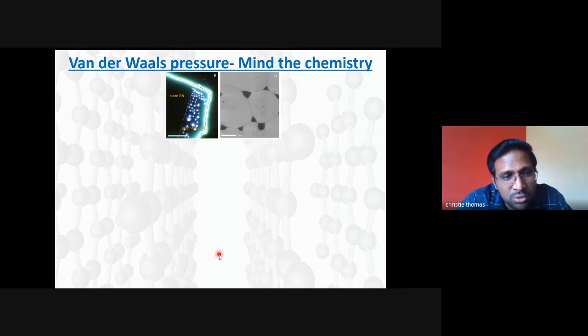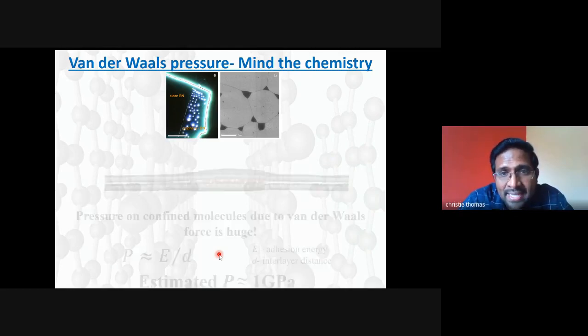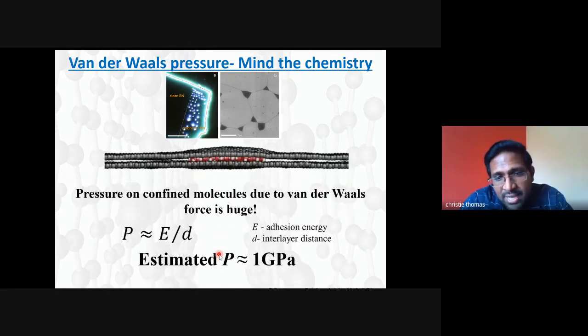The trapped molecules are predicted to experience pressure as high as 1 gigapascal. Okay, estimated pressure is 1 gigapascal. Okay, so what is the significance of this? Because this pressure can induce chemical reactions which can happen only at high temperatures. This high pressure can induce chemical reactions which may happen only at high temperatures.